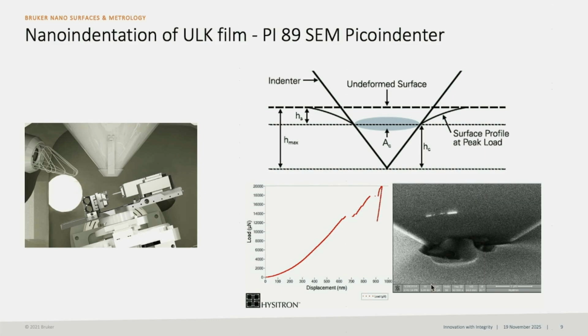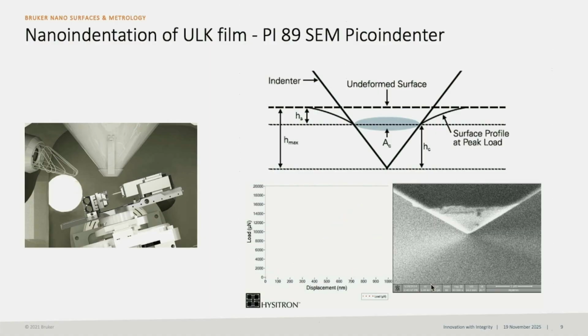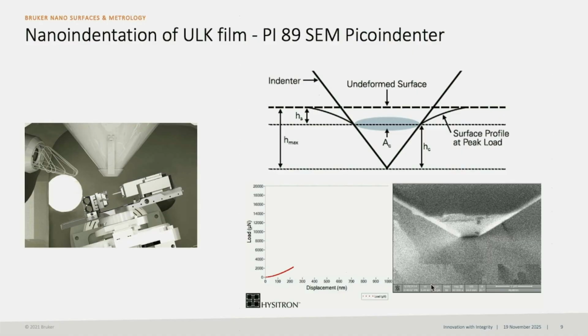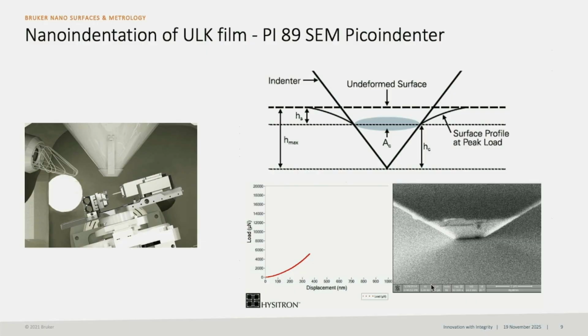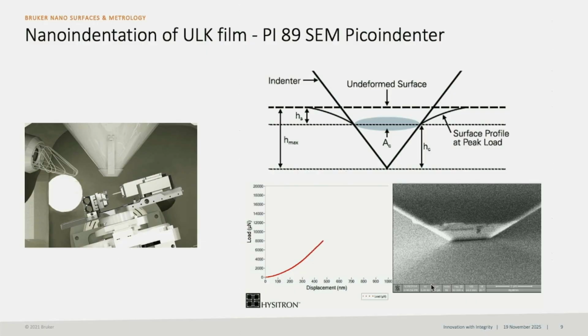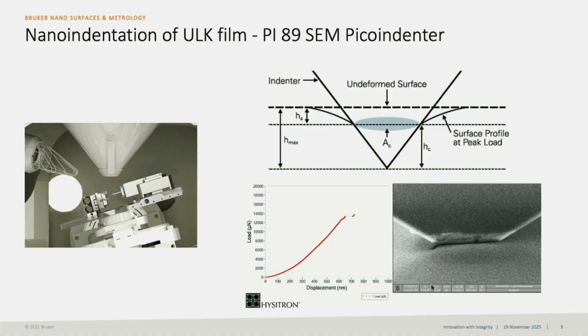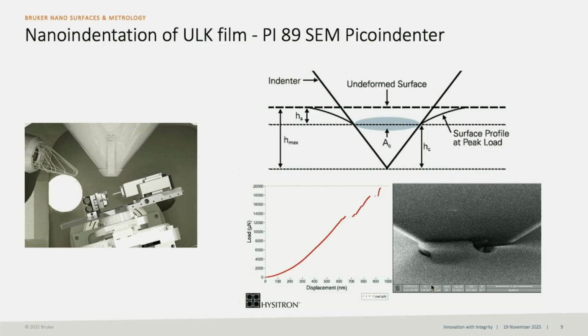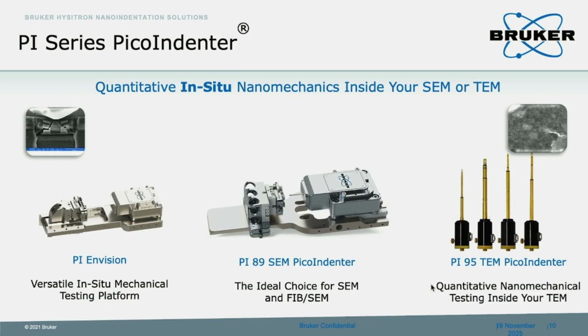So the first pop-in is about the cracking. That is about the fracture toughness of the material. The second is about the thin film delamination. So this video just tells us the nano indenter can tell us not only about the hardness and the modulus. We can use the nano indenter to see other mechanical properties as well. But the most important thing, again, is that we still need the in situ image to help us understand what happened here, right? So this is our core technology, we call the in situ nano indenter inside of the SEM.